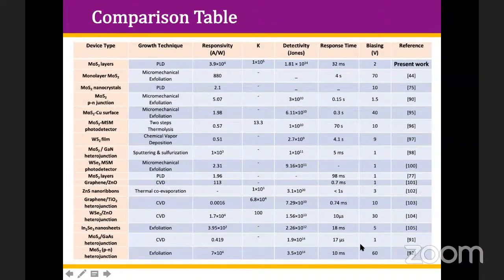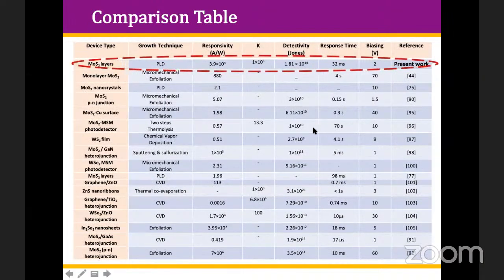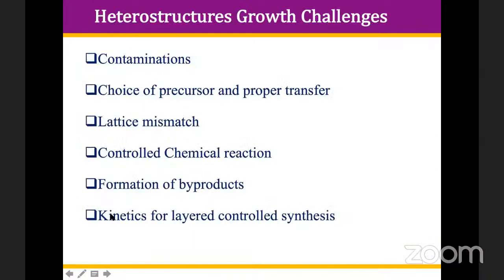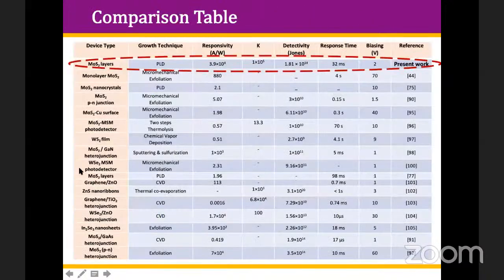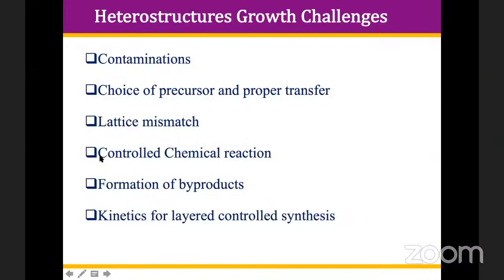So this is the literature. From literature we have compared, and you can see our values of responsivity, detectivity, and on-off ratio are found to be much higher as compared to the values reported by other people using other techniques, mostly sputtering or chemical vapor deposition techniques. So you can see the advantage of pulsed laser deposition. In this case, just for comparison, we have put some other materials also so that you can compare MoS2 with heterostructures of other materials and see the results.